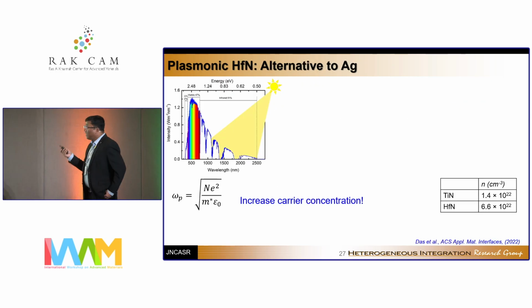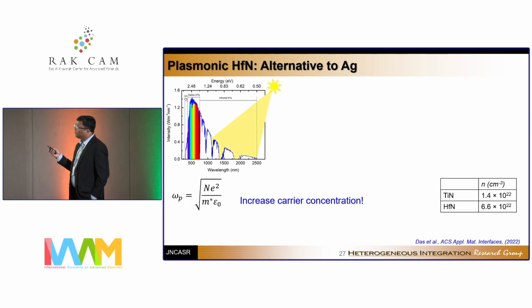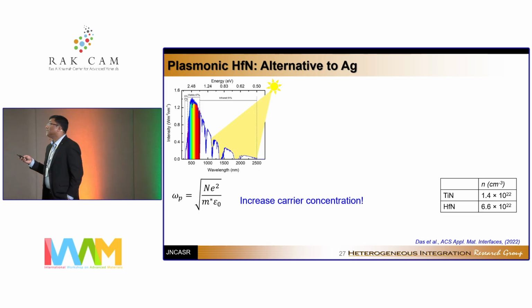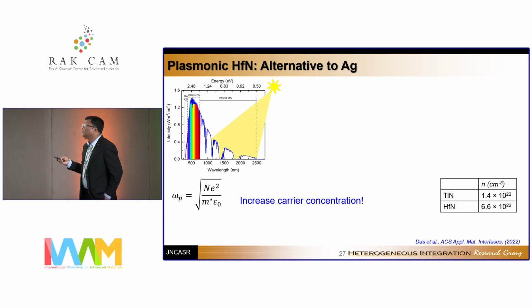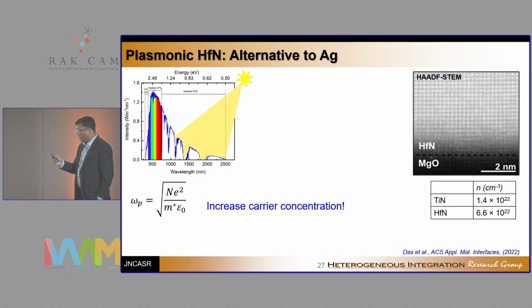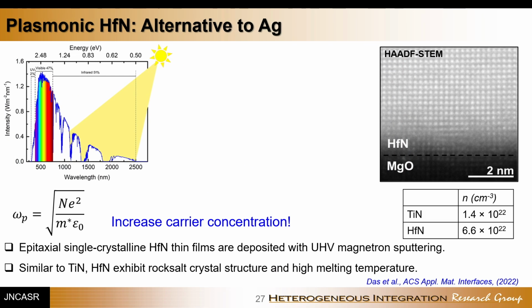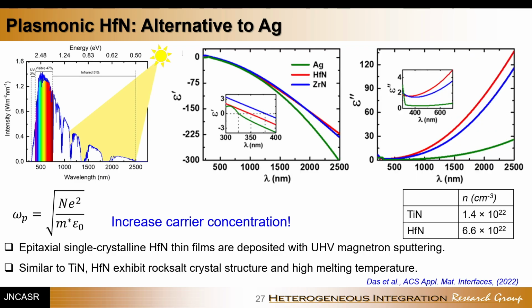What we have done is, with some research, we have demonstrated that transition metal nitrides, for example, titanium nitride and hafnium nitride, are a very good replacement for gold and silver. So in this particular case, hafnium nitride, which is a 1-to-1 hafnium mononitride, when we deposit it under high quality, high temperature epitaxial growth conditions, we showed that hafnium nitride actually acts as a very good replacement for silver for something known as solar mirror application.